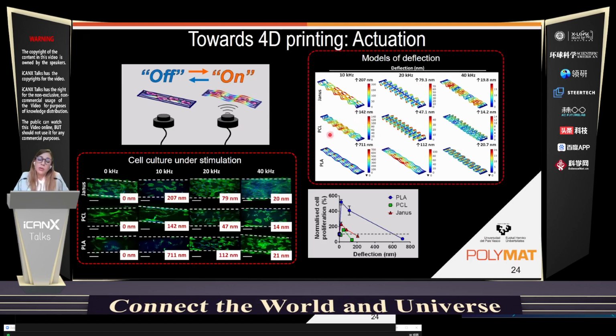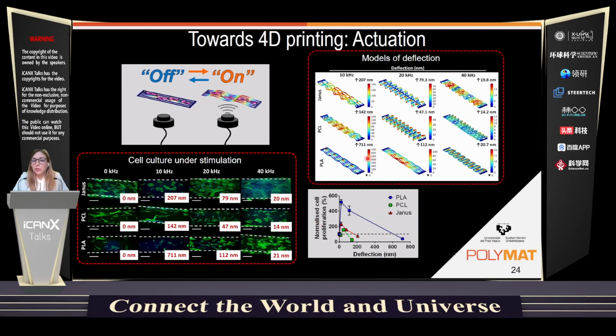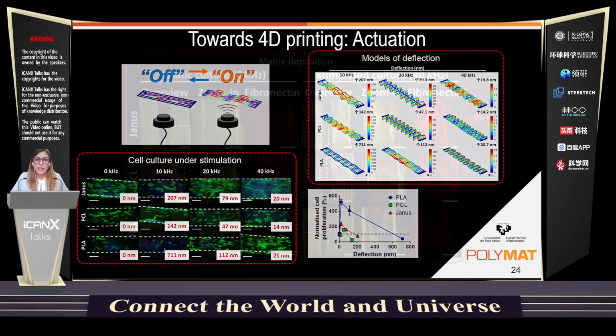Now, when we culture cells on top of these materials, what we observe is that the growth pattern, the proliferation, was also dependent on this amplitude of deflection. So at higher amplitude, some of the cells were dying. At lower amplitudes of deflection, corresponding to the 40 kilohertz, they were proliferating at a faster rate, having the highest proliferation on PLA scaffold, followed by Janus, and finally PCL scaffold. So that makes sense, right? This proliferation is related to the amplitude of the deflection.